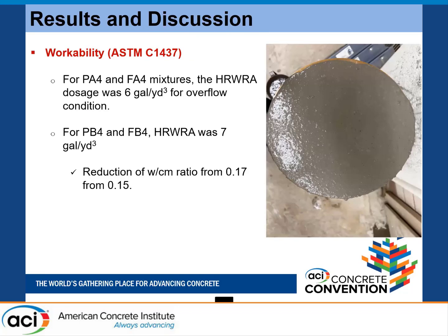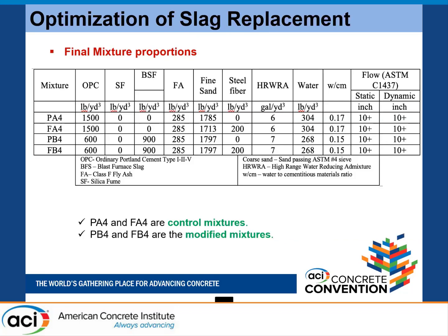In the A series mixes, 0.17 is the water binder ratio. In the B series mixes, the slag mixes, we were able to reduce the water binder ratio from 0.17 to 0.15 and still achieve the same spread. But there is a slight increase of 1 gallon per cubic yard in HRWR, the high range water reducing admixture, because slag does not produce a ball bearing effect like fly ash. So we increased the high range water reducing admixture a little bit, but that's it.